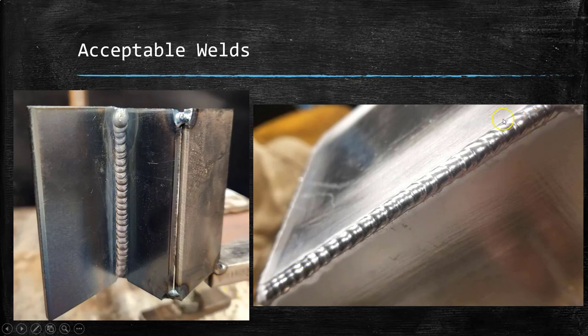And then over here we have a weld on aluminum, and same thing, everything looks nice and shiny and uniform. There are no matte white or very bright white looking areas. Now, white and silvery will appear in two different ways. So this is kind of silvery. If you see anything white, it's going to be very apparent. It looks like you've put a little section of printer paper on there. And likewise with any kind of black soot spots, you see that this weld is free from any of that. And you do see some markings from this person using a wire brush. So even with aluminum, you need to use a wire brush or you need to clean the surface of your material. If it looks clean, doesn't mean that it is clean.